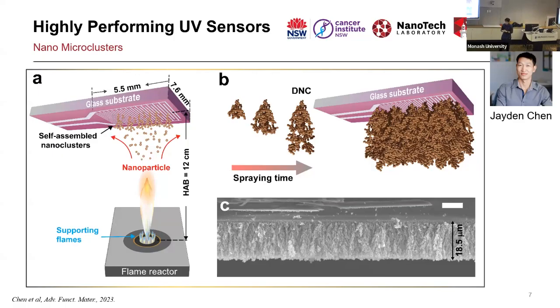And then just one follow-up question. Can you also apply this to material with plasmonic effect, like silver or gold? We can. With silver, it's a bit tricky. Sometimes it gets oxidized inside the fire as well. With gold, platinum, palladium, we tried. Absolutely not a problem. With silver, we ended up with both silver and silver oxide.